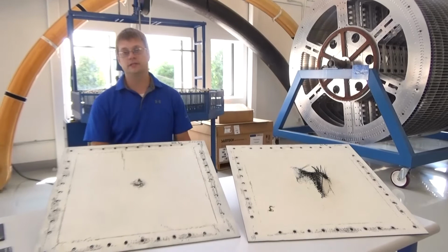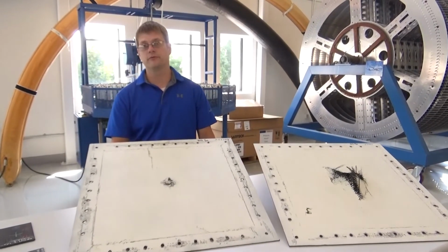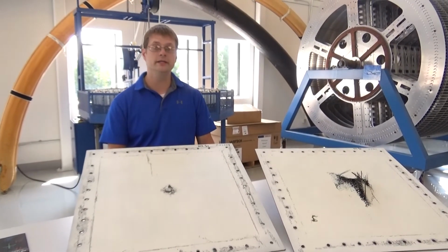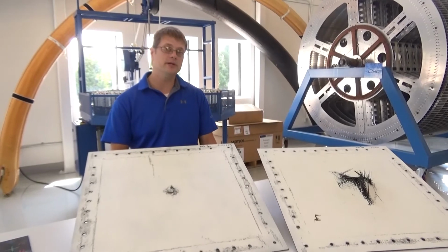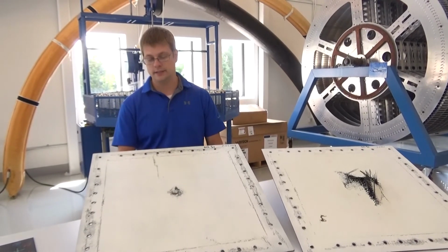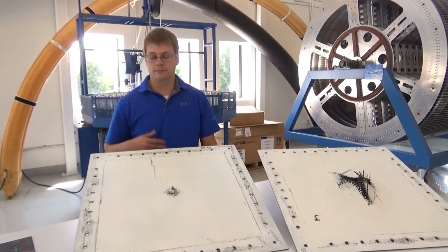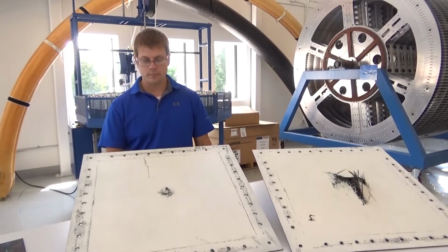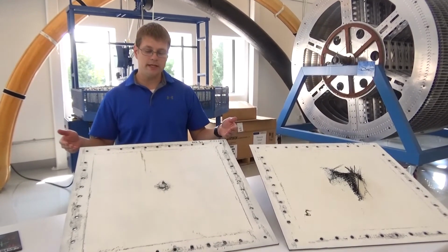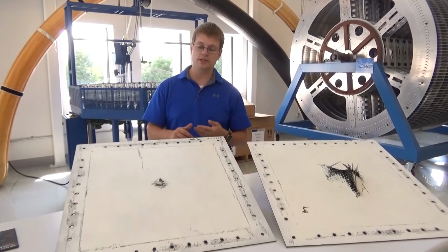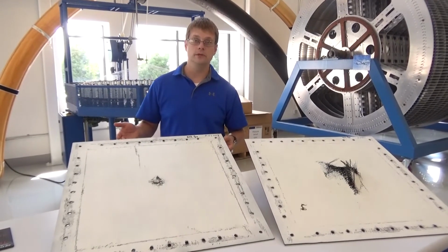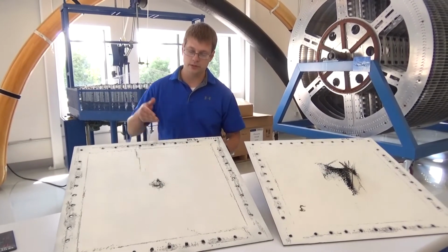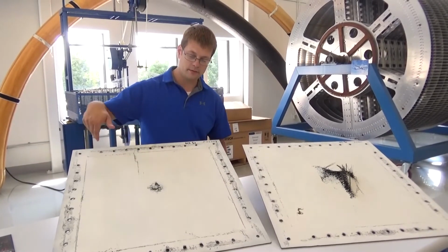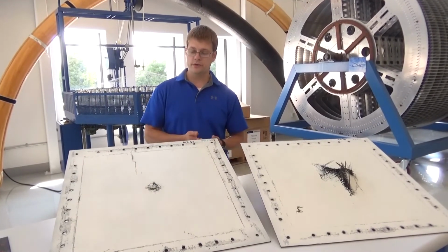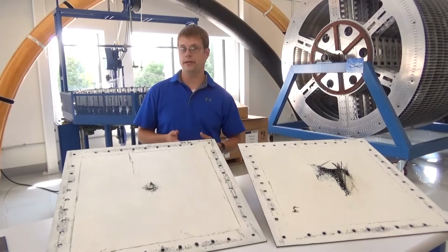Our QISO material has been well known for its impact performance, and because of that, it's widely used in ballistic applications such as fan and containment case systems, really where impact performance is paramount. The reason why QISO does so well is because it's quasi-isotropic in a single layer. You have 3 axes of orientation, 0, plus 60, minus 60. Each one of those layers is going to react the same way when impacted.